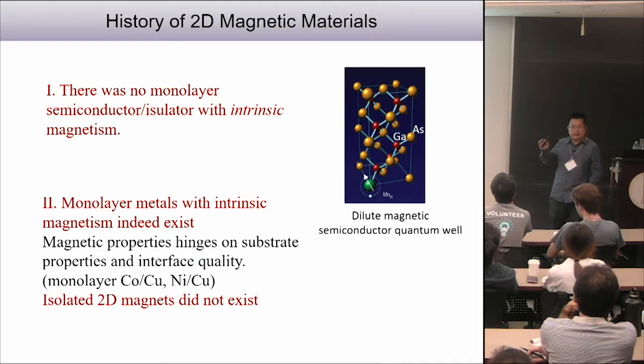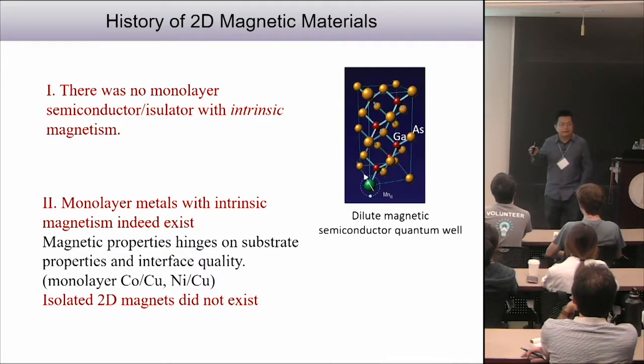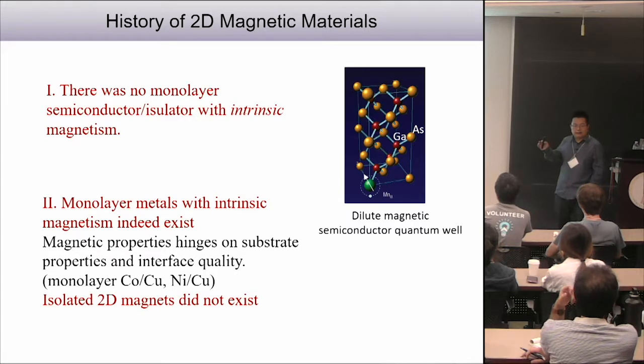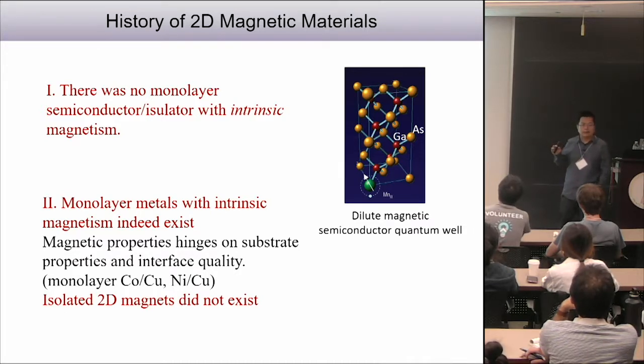two-dimensional magnets, they usually use sputtering or MBE, right? So those are kind of challenging techniques to go really thin because, for example, with MBE you can go to monolayer, but you cannot grow any monolayer on any material. The substrate is really important. So epitaxial matching, right, is really important.